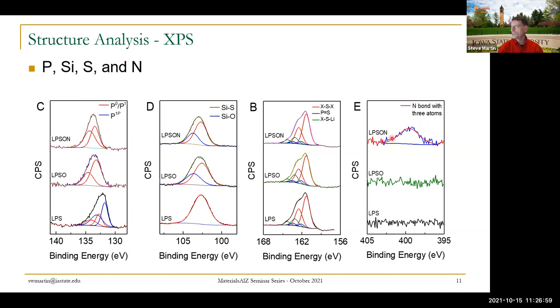And this tricluster seems to be the only one present in our glasses. We're working to understand that in more detail, but suffice it to say, NMR and other spectroscopies allow us to identify the phosphorus and the silicon and the sulfur. The XPS allows us to identify the nitrogen structures. And it looks like we have this threefold tricluster, which is a very strong cross-linking species, which might explain the slightly higher Tg and might explain the slightly larger working range before crystallization.